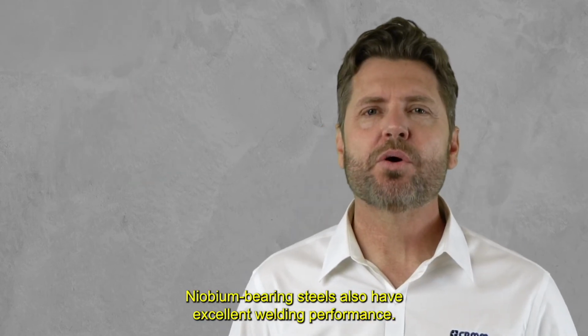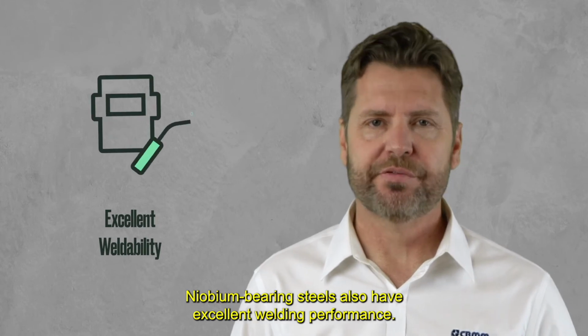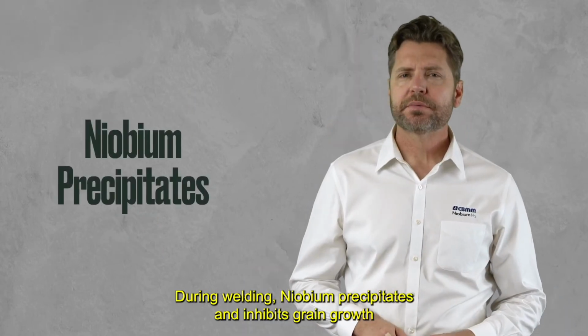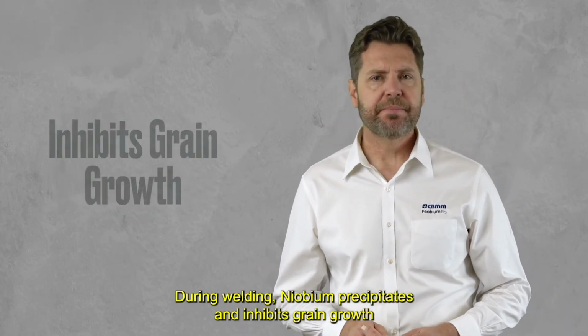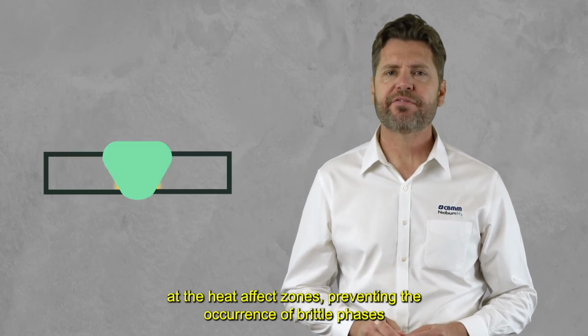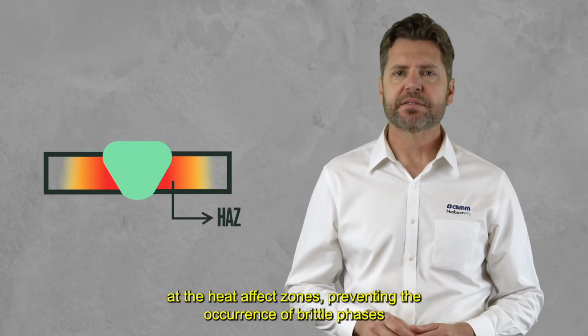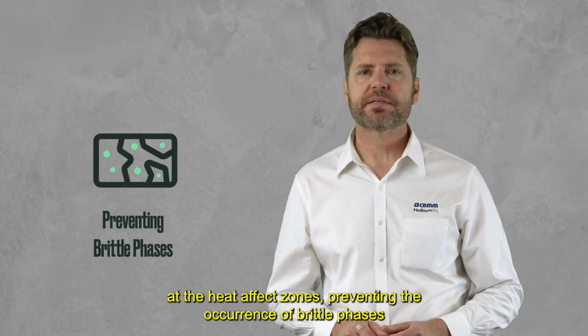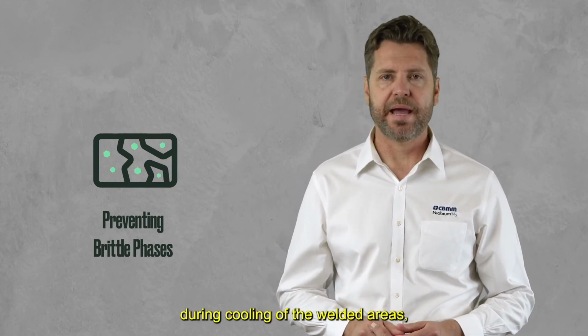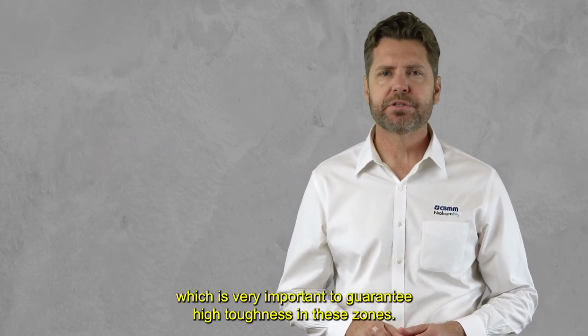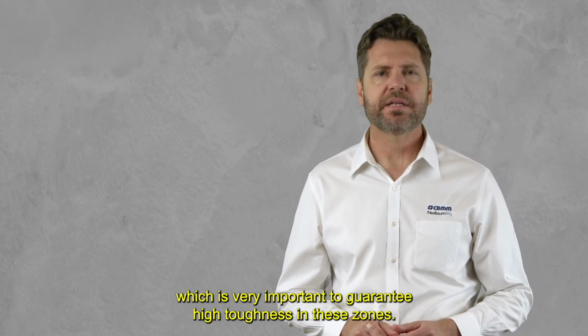Niobium-bearing steels also have excellent welding performance. During welding, niobium precipitates and inhibits grain growth at heat-affected zones, preventing the occurrence of brittle phases during cooling of welded areas, which is very important to guarantee high toughness in these zones.